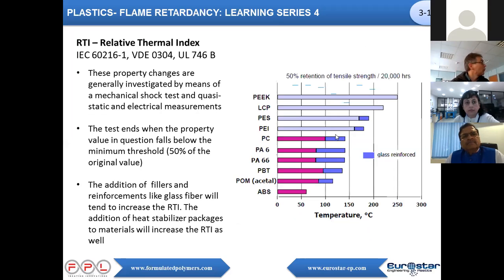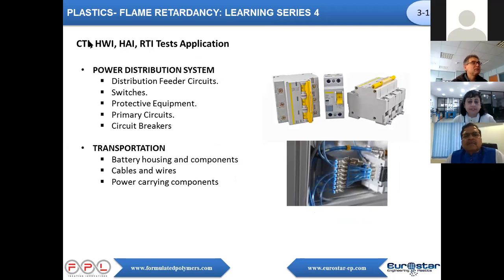I have to go fast because I see I'm almost late. But you see on the material properties for standard material, you see the RTI ranging across different polymers. And you see that nylons, polyamide 6 and polyamide 6.6 have already a good RTI that can be boosted with glass fiber and with stabilizer. And in our case, we have materials with RTI above 150 degrees C. So this is really a strength. It applies mainly to power distribution systems, for feeders, switches, protective equipment, circuit breakers, more and more in transportation, for battery housing, cable, power carrying components, and with time, it will really come for electric vehicles.